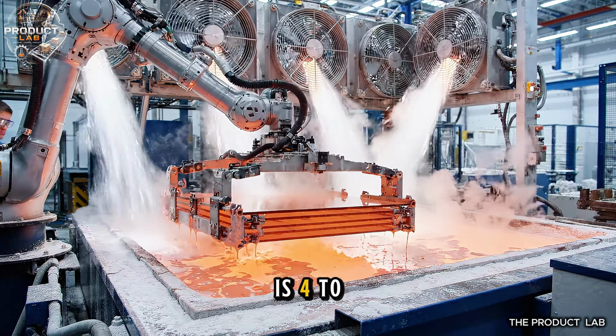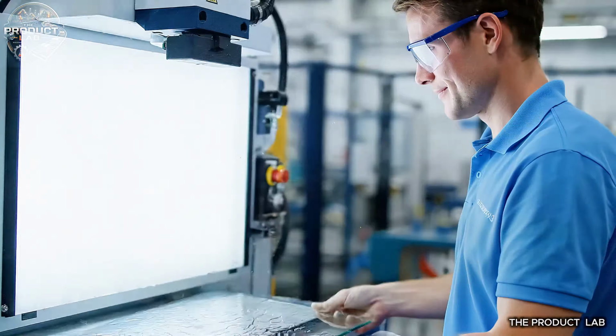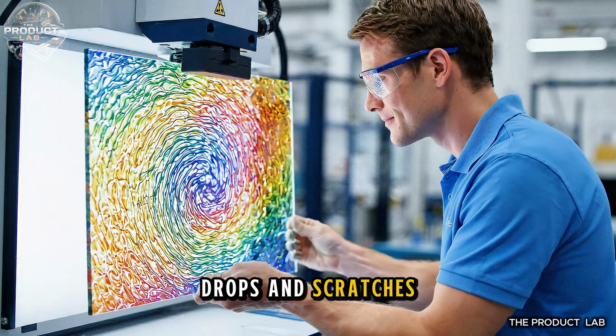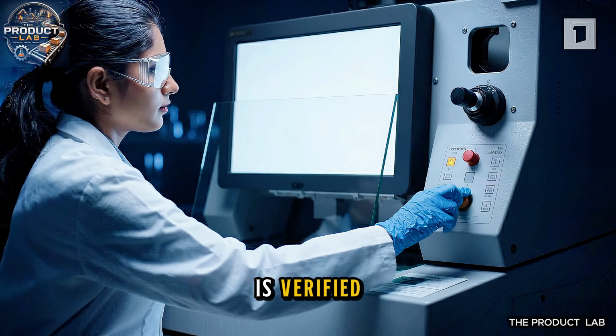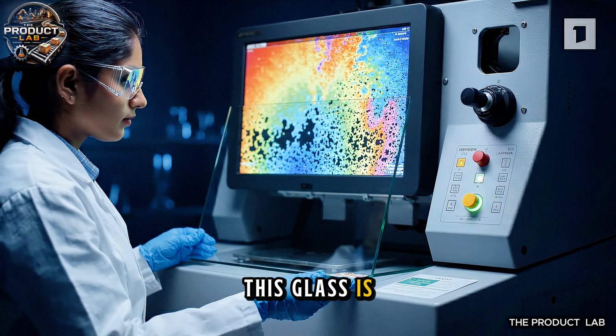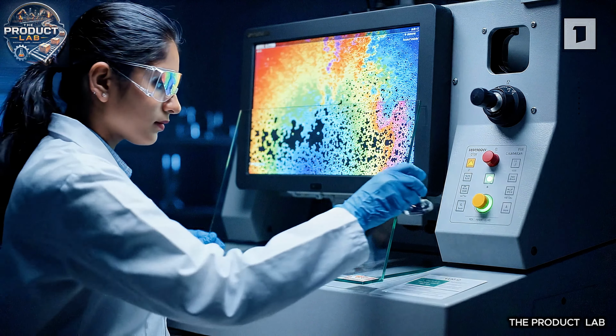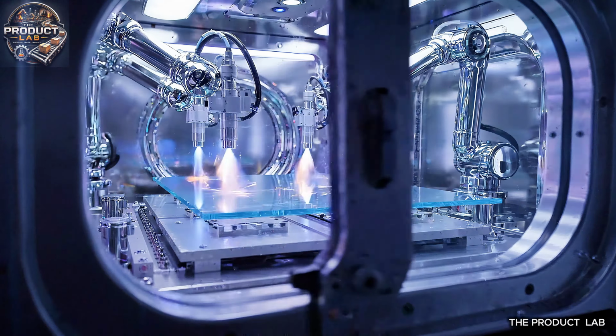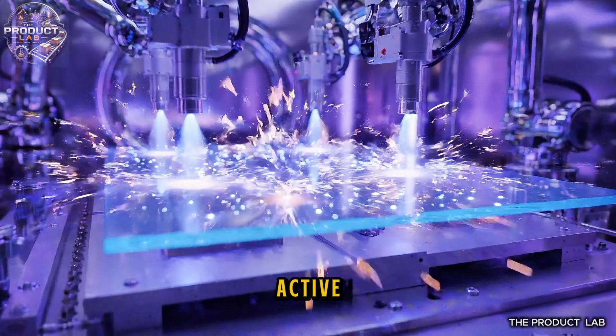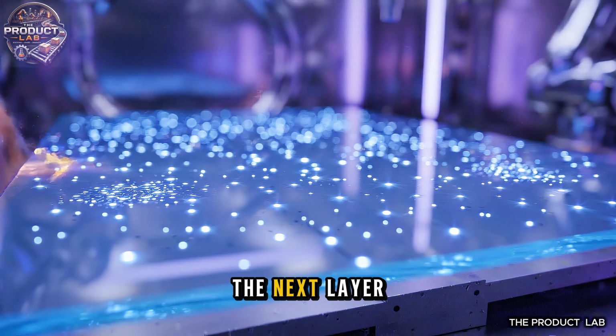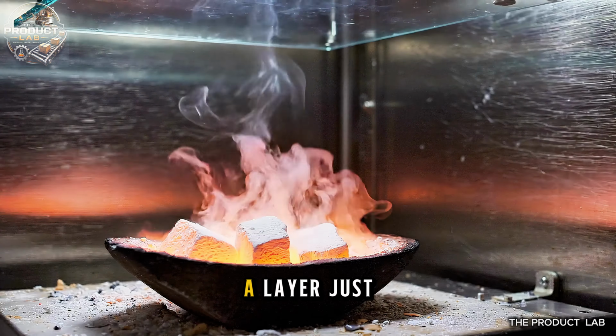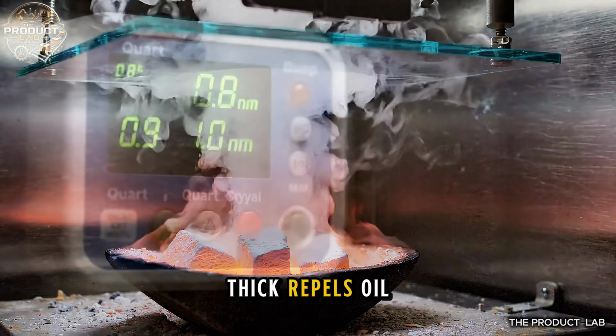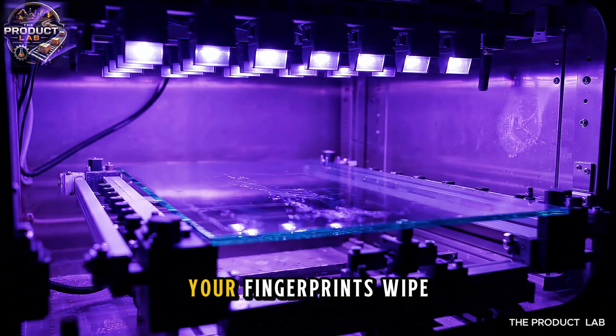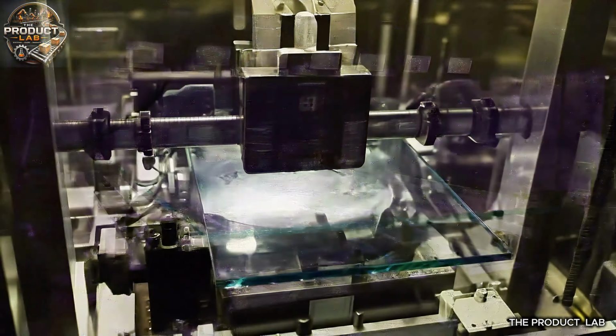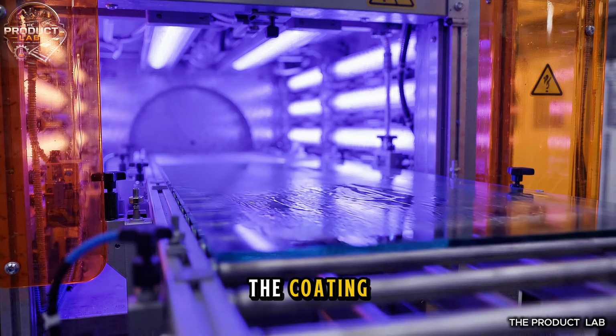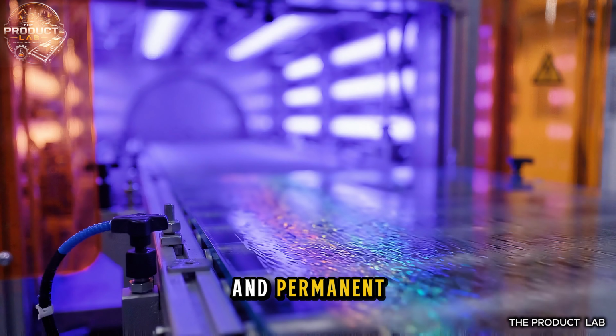Now the glass is 4 to 5 times stronger than before. It can survive drops and scratches. The stress layer is verified. This glass is now ready for the toughest tests. Plasma cleaning makes the surface chemically active, perfect for bonding the next layer. A layer just a few molecules thick repels oil and water. Your fingerprints wipe away effortlessly. Ultraviolet light cures the coating, making it durable and permanent.